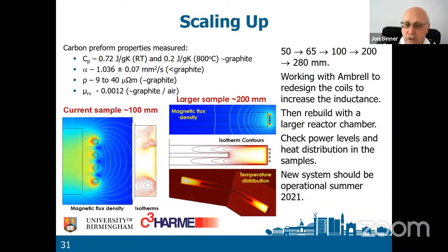We've also focused on scaling up. A lot of our work was done at the beginning on quite small samples, 50 millimeters, but we did a lot of work including modeling of the whole RF process. So we could go from 50 to 100, and then we want to get to 200, and then we want to get to 280 millimeters.